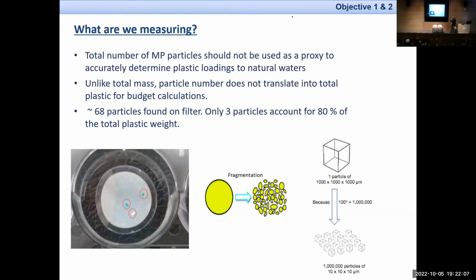So for example, I'm going to show you this. This is a filter, like the one they use for coffee. But this is a special filter that we use to study plastic, but it's the same concept. So everything that is retained here, we can study. We collected in this filter around 68 particles of plastic. 68, we counted 68 particles. The problem was that these 3 particles that you can see here in the red circles account for 80% of the mass of those 68 particles.